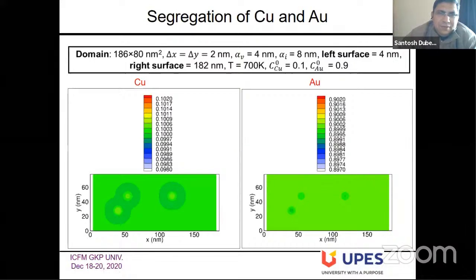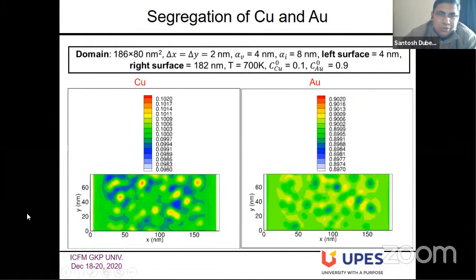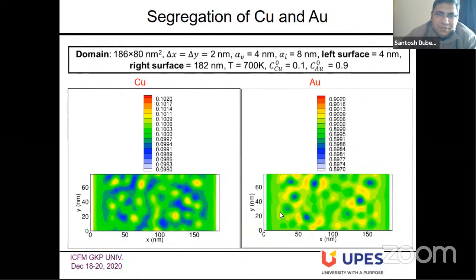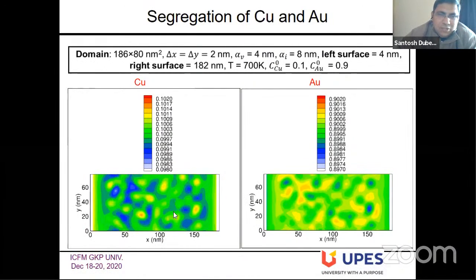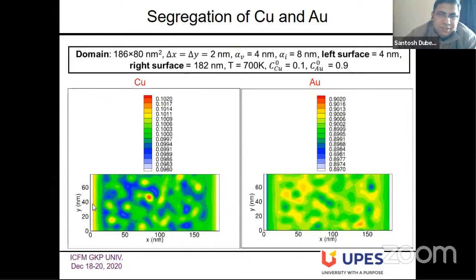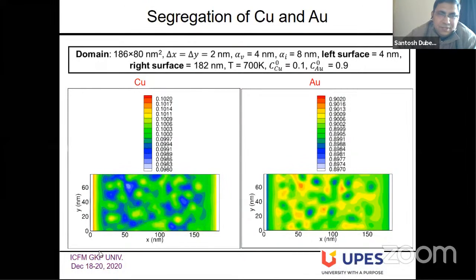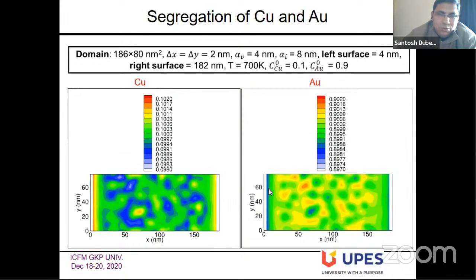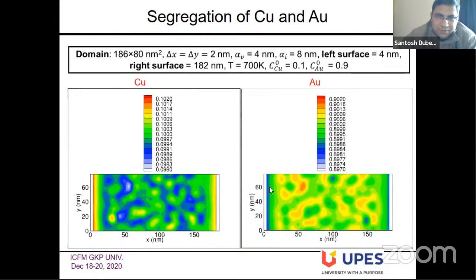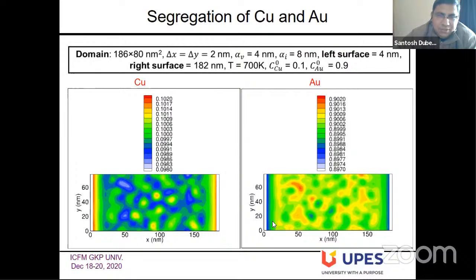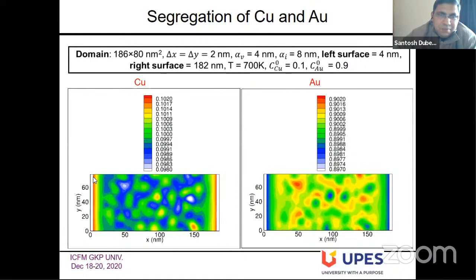Similarly, for the segregation case, I used the same model with different boundary conditions to study segregation. These are interesting simulations. At the left and right, we have free surfaces in both cases. In one case, copper is a faster diffusing species. It goes and sits near the free surface, and gold comes inside. So you have depletion in the gold, and enrichment in the copper.